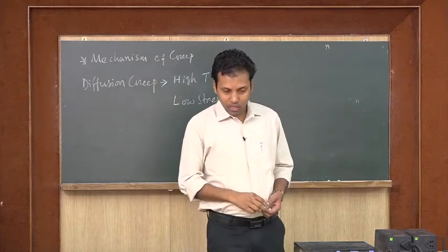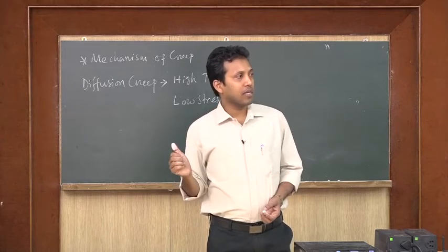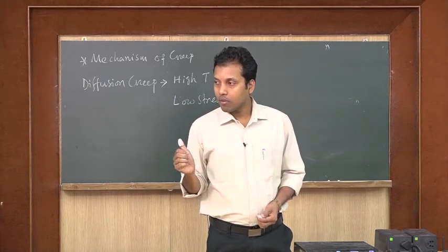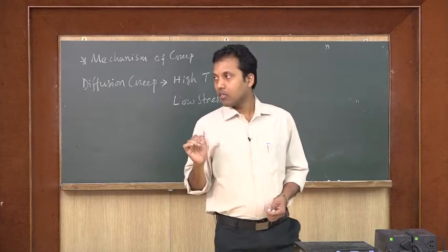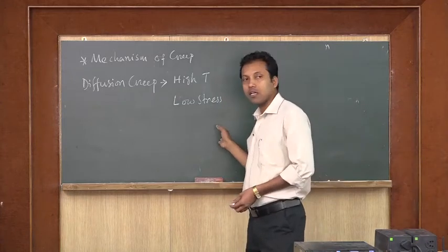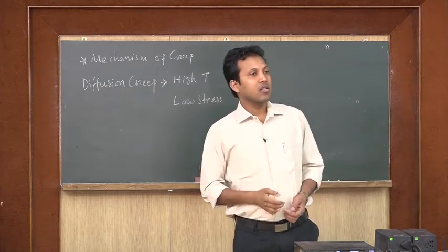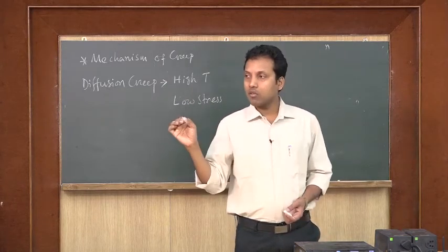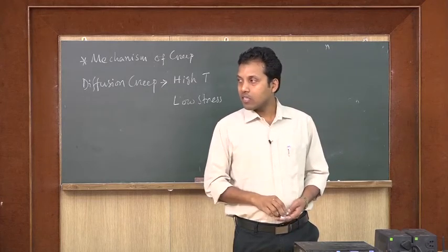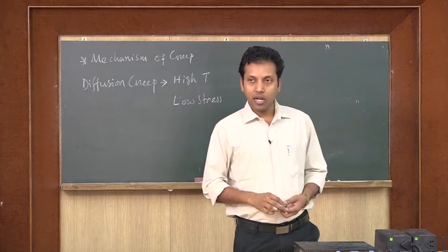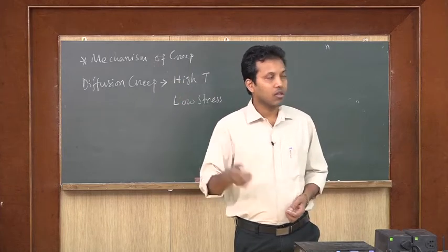So what we have seen earlier is there is dislocation glide, and then due to the presence of temperature, some certain temperature which is above the homologous temperature of the material, there is some climb. So that way the dislocation actually controlled the creep behavior, or rather as soon as this climb is happening, then only the creep deformation is going on, isn't it?